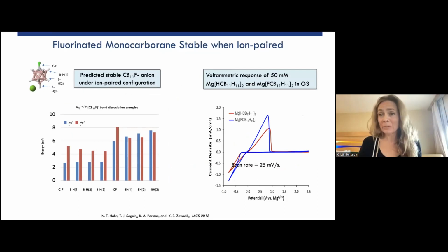And Nathan was able to make it and purify it. And you can see the result on the right there. We compared the original monocarborane and the fluorinated version. It shows a nice, clean plating and stripping profile. So again, it seems to work quite well. It retains its ability to work well with the metal. And this is in triglyme.